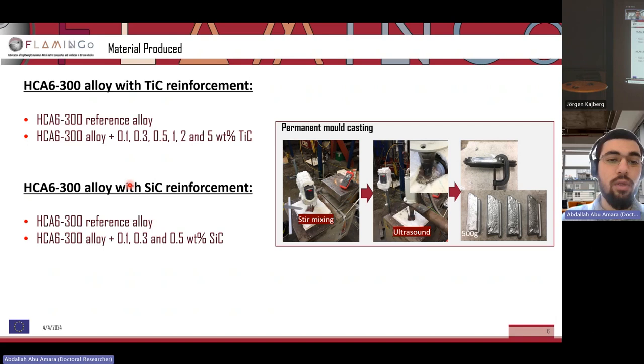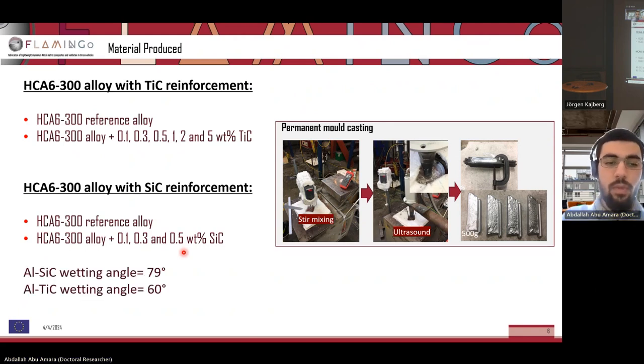And for the silicon carbide, again, we cast the reference alloy, just the HCA6 300 by itself. And then we also added, in this case, for silicon carbide, 0.1, 0.3, and 0.5 weight% silicon carbide. The reason why we were only able to go up to 0.5 weight% silicon carbide, whereas with the titanium carbide we're able to achieve more, is related to the wettability of the materials.